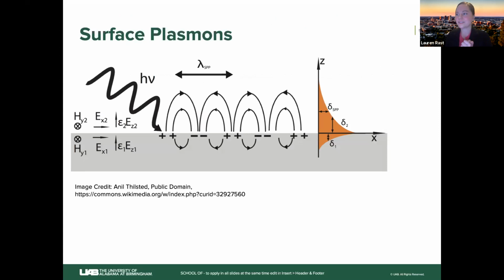Okay, so I'm talking about surface plasmons quite a bit. Quantized units of plasma oscillation, as I said, are known as plasmons. And when the real part of the dielectric function in a medium changes sign across some interface, as I've shown in gray here, that boundary where a metal and dielectric share this boundary, we get something called a surface plasmon resonant mode. Okay, and these are really important in optoelectronics applications. These surface plasmons can couple strongly with a wide variety of collective oscillations and quasi particles to form other quasi particles and collective modes.